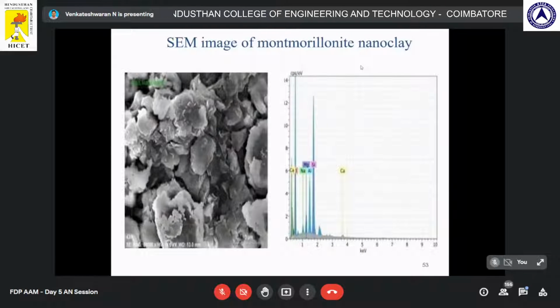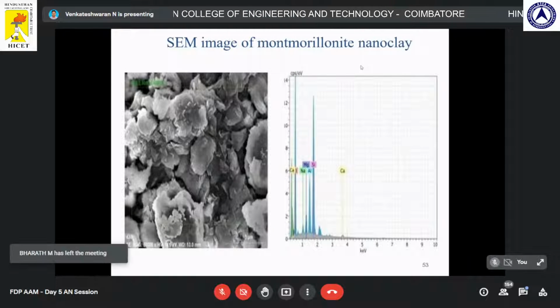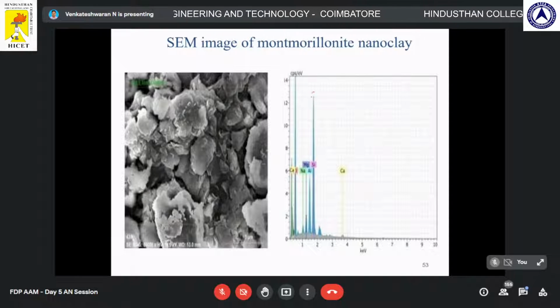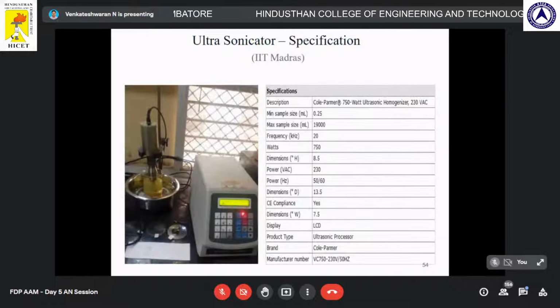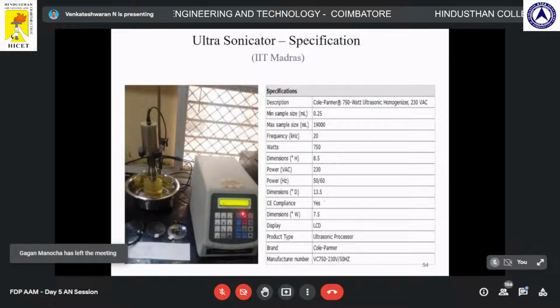So first the nanoclay was observed in the SEM with EDAX to show the material with silica as the peak. Okay, the silica material with a peak value. So it confirms that it is made of silica as the maximum material. Second thing, we used the ultrasonification process with a bath, right? The frequency in which we can operate is a maximum of 20 kilohertz, right?